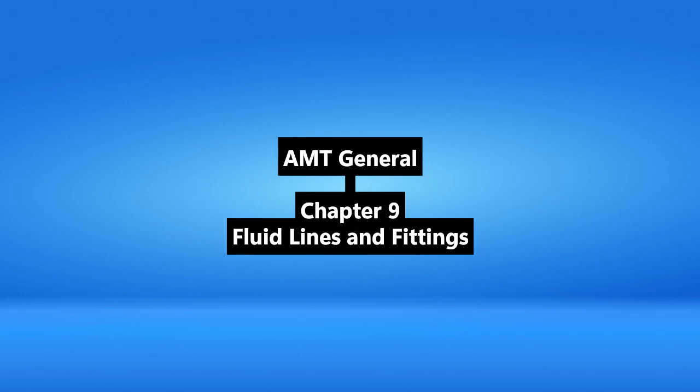Okay. But there's a big warning about titanium, isn't there? Something about oxygen. Absolutely critical. Cannot stress this enough. Titanium and its alloys are highly reactive with oxygen. Reactive how? If a fresh titanium surface hits gaseous oxygen, even at low pressures, it can spontaneously combust. Wow. Okay. So keep titanium far away from oxygen systems. Completely separate. Always. That's one of those details that really highlights the level of care needed. It's a fundamental compatibility issue.